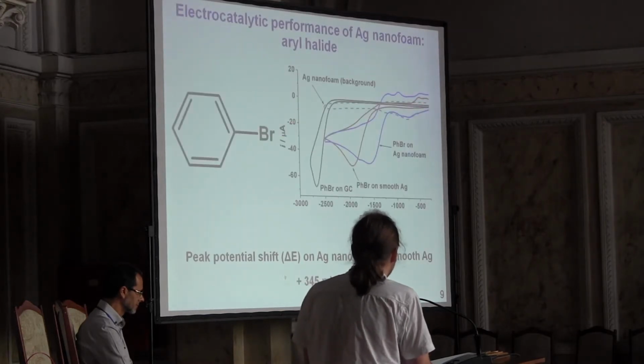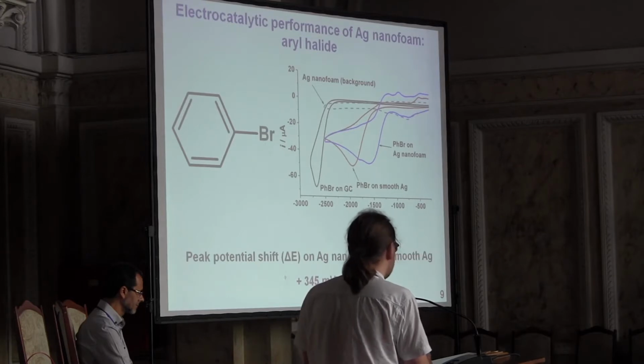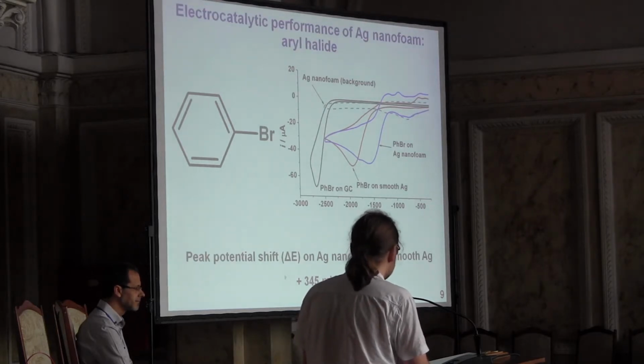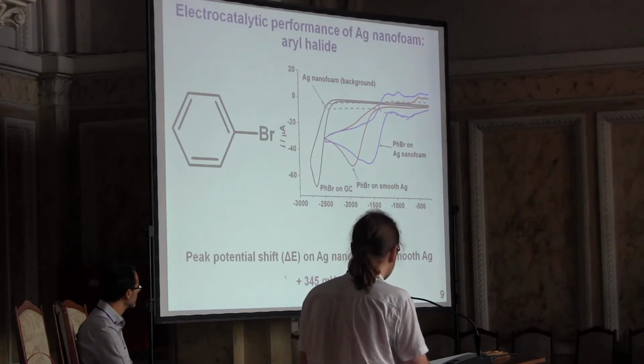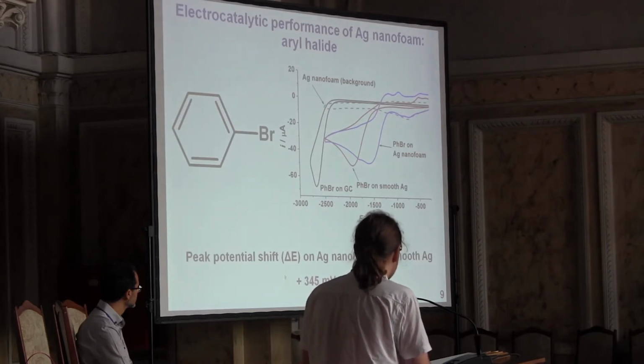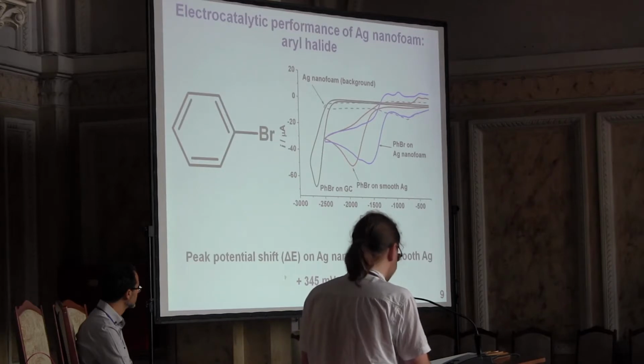The same situation as for alkyl halides was observed in the case of aryl halide, namely bromobenzene. It should be noted that in the case of this compound, we observed the highest potential shift in the entire work, about 350 millivolts.